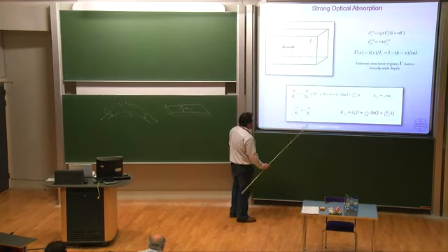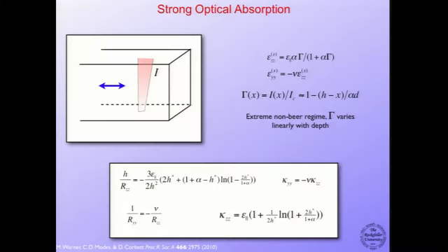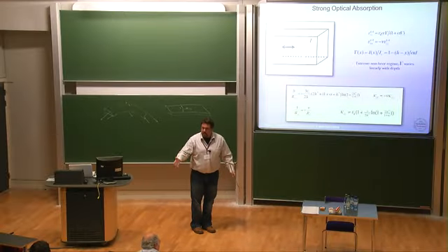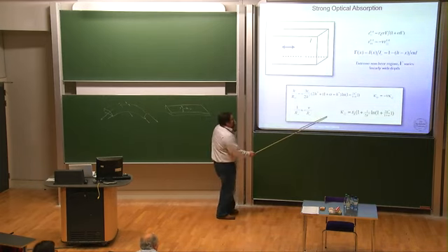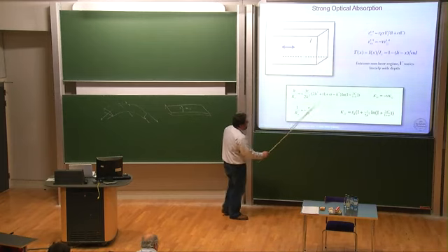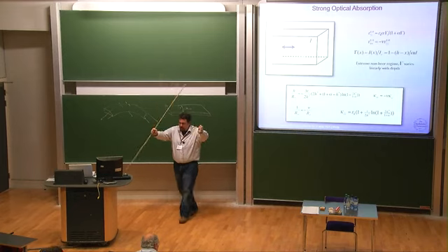approximation that I've written down, you get some formula that depends on two different relative parameters. There's the same relative thickness as before, and now there's a relative intensity, right? So now the intensity as a function of the depth is being scaled by this IC, which is a quantity related to the degree of back reaction of the molecules, right? So you have the molecules, some of them are turning, and then the relaxation occurs. So you get a repopulation as a function of some time and intensity, in the steady state. And so IC is telling you about that. And so you get this much more complicated thing, and you can imagine there are more knobs to turn.